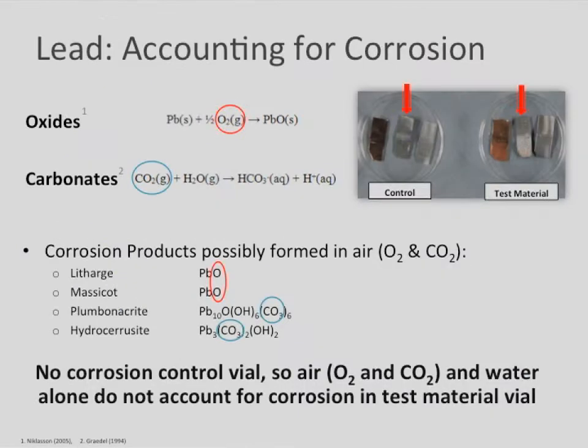And so we asked the question, where are these coming from? The control, which has air and moisture in there, doesn't form a lot of corrosion products—so why don't we see a lot of crystals forming on that? Because in air you've got oxygen, you've got moisture, you should be able to make lead oxide, and then we've got carbon dioxide in the air. Why is that not forming lead carbonate?